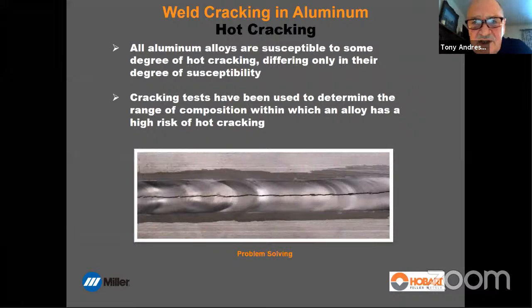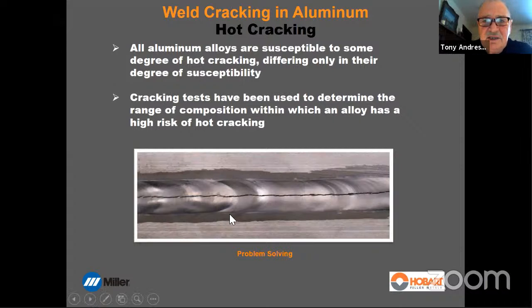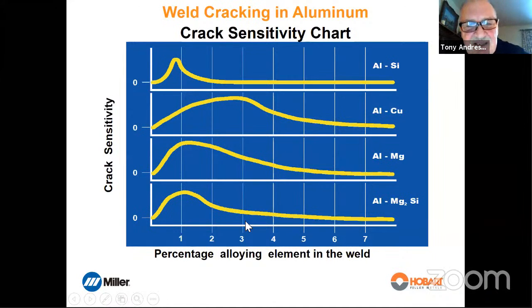Okay, so all aluminum alloys, I said this, are susceptible to some degree. It differs only by the degree. All right, cracking testing has been used to determine the crack sensitivity. So we're going to look at the crack sensitivity curves, and here they are. You'll find these published in a number of documents now, but they were very well hidden for many years for some reason. But anyway, what we're looking at is four individual crack sensitivity curves here. We've got silicon in aluminum, copper in aluminum, magnesium in aluminum, magnesium silicide, Mg2Si in aluminum. And we see the amount of those elements and how it affects the crack sensitivity.